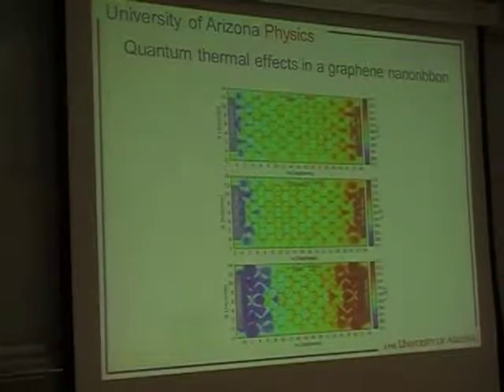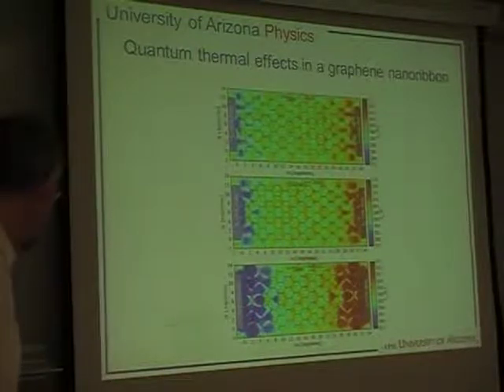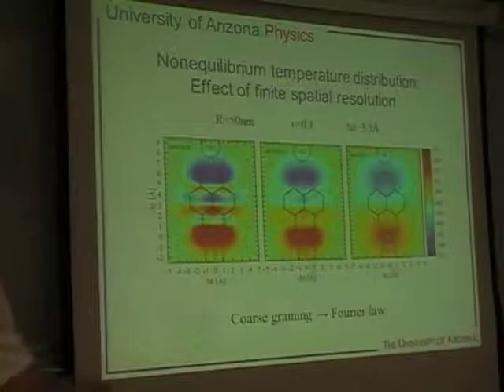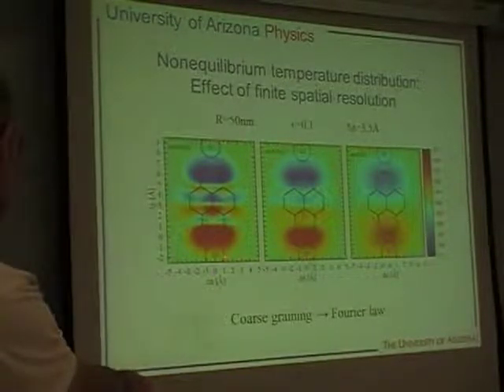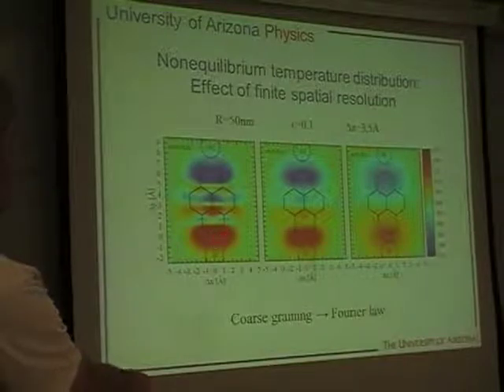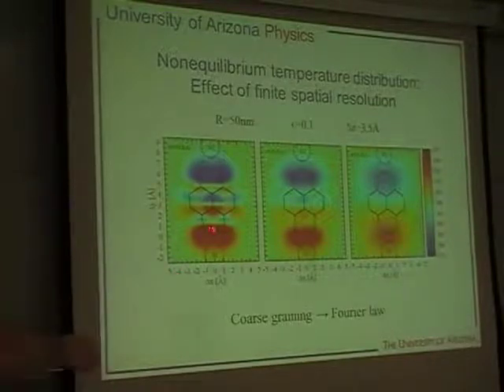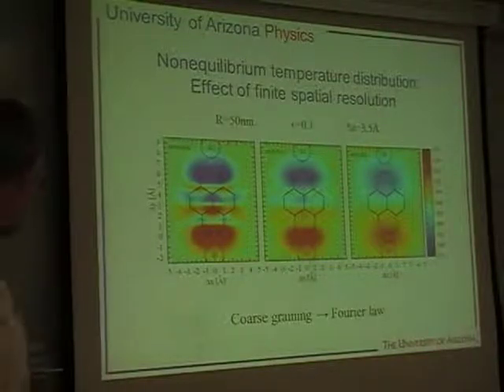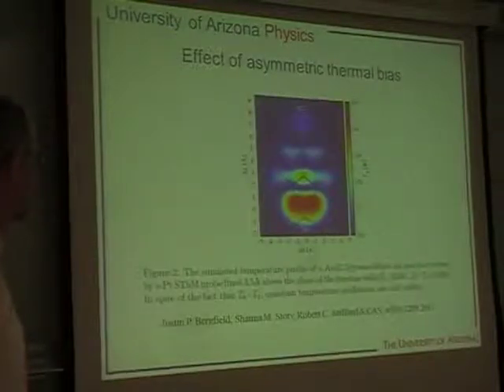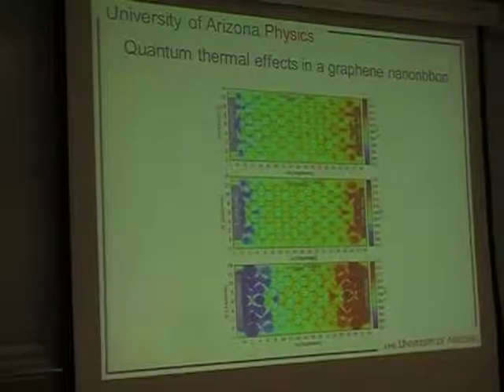But all this may seem very academic, because if the current state of the art is 10 nanometers, and I'm telling you that we should look for these oscillations on a length scale of, here, 1.4 angstroms, so the wavelength is roughly 2 to 3 angstroms, that's a couple of orders of magnitude away from what the experiments can do. But there are other systems that you can study, and in particular, I think graphene is probably the best candidate system in which you could observe these thermal quantum effects.